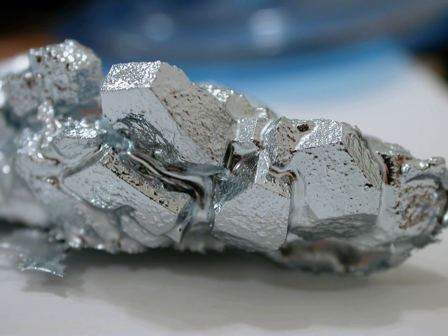It can be made by the reaction of gallium with hydrogen sulfide at 950 degrees Celsius. Alternatively, gallium(III) oxide can be used at 747 degrees Celsius.